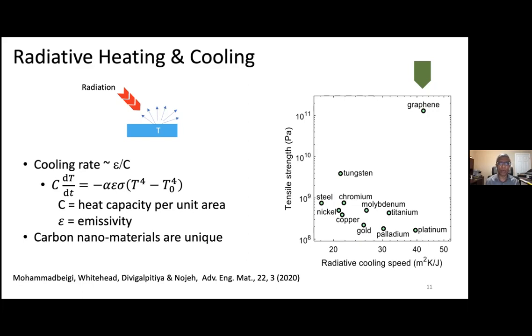So if you look at a small piece of graphite or graphene, the cooling rate after heating, you can show easily, is proportional to the emissivity divided by the specific heat per unit area. So if you plot that ratio for all the known materials versus the tensile strength, or the other way around, you can clearly see that graphene and carbon materials are pretty unique. They occupy a very unique place. So hopefully some applications will come out of that capability of this material. So I'm just trying to highlight the uniqueness of this material.